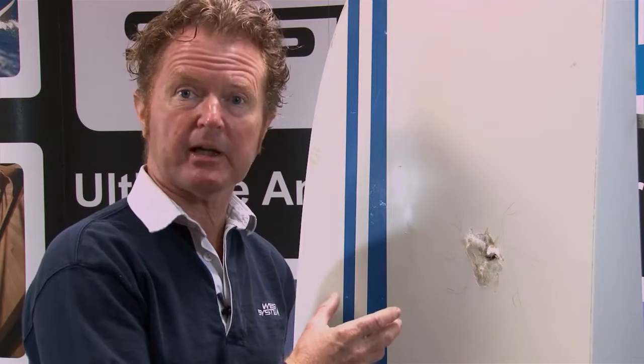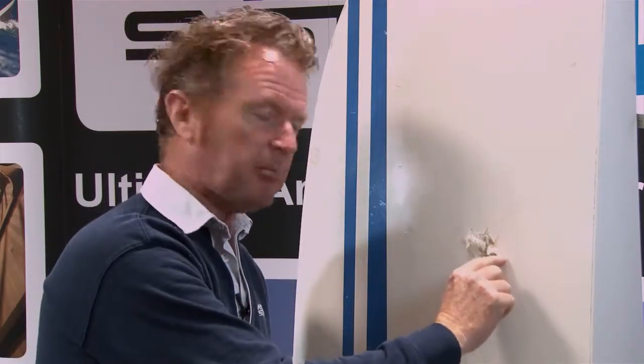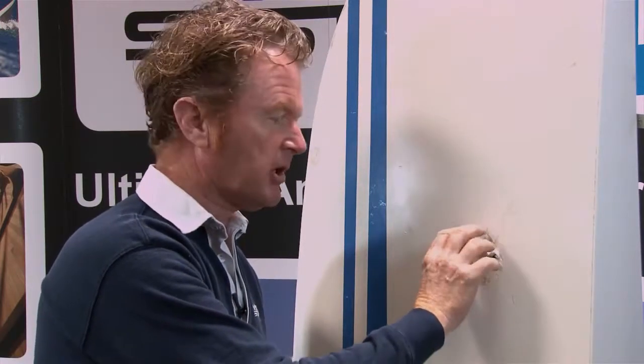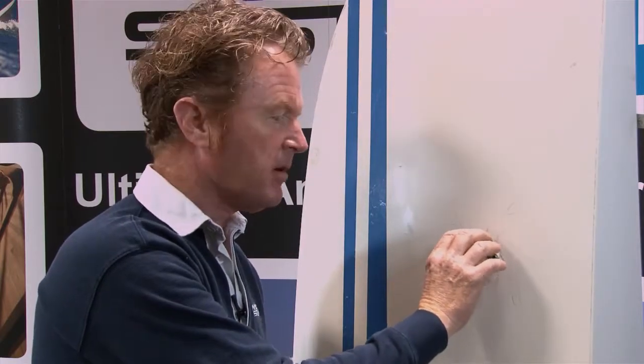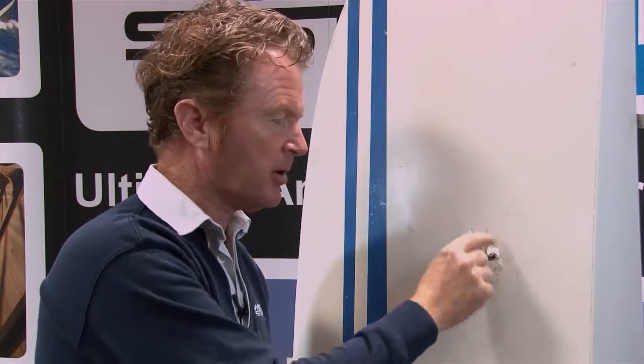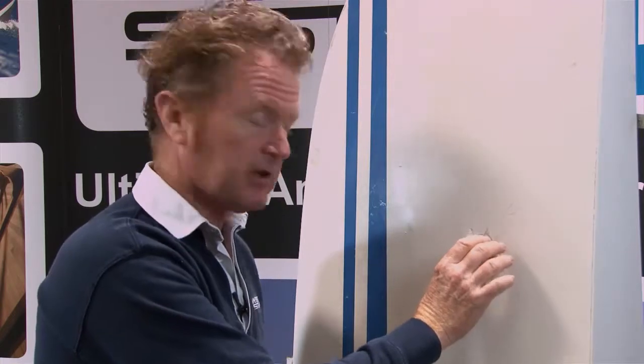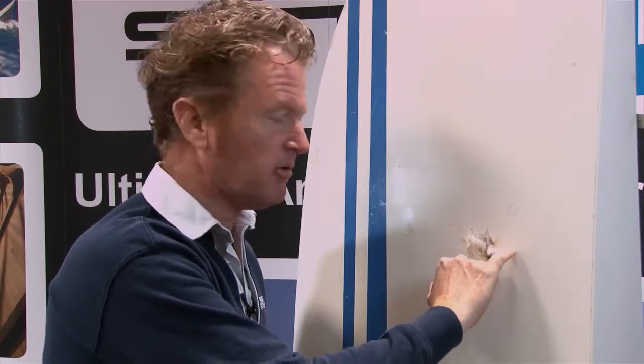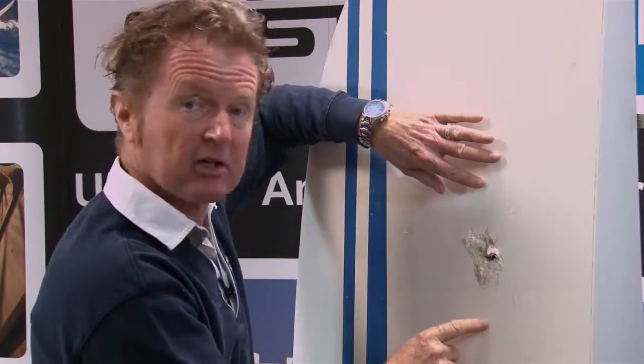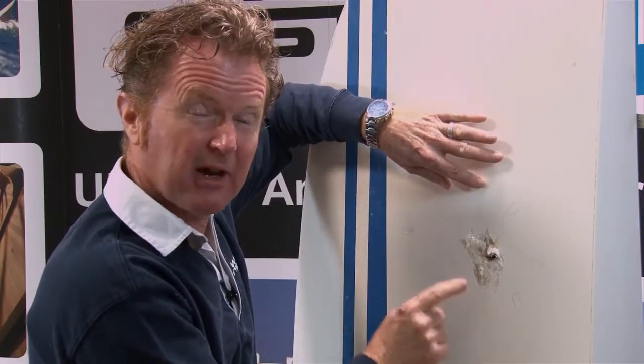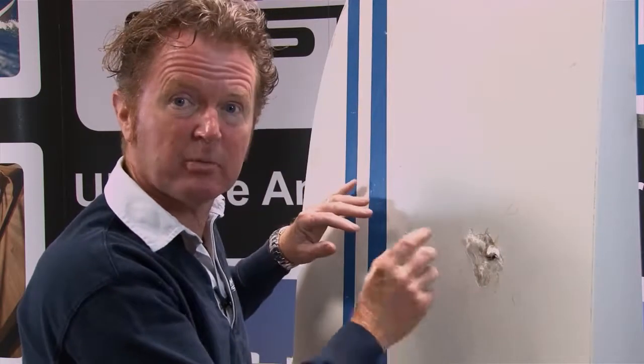But the first process is to assess the extent of the damage. This is very clearly covered on another video called Assessing GRP Repair. It's very important that you look closely, because the point of impact may well be very small. And on a thin laminate such as this, the point of impact is quite small, the size of a teaspoon. But in fact, the star crazing that occurs around the perimeter of the damage may extend actually to the size of a dinner plate. So it's very important to assess this damage before proceeding.